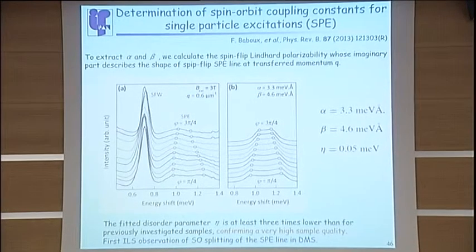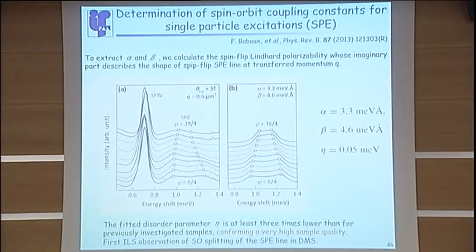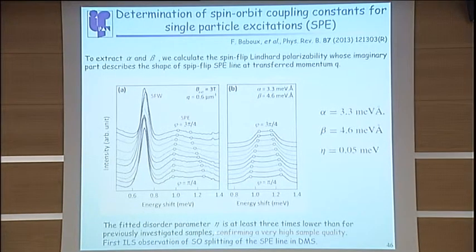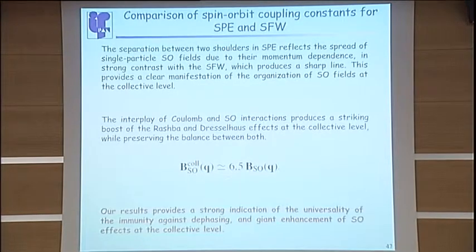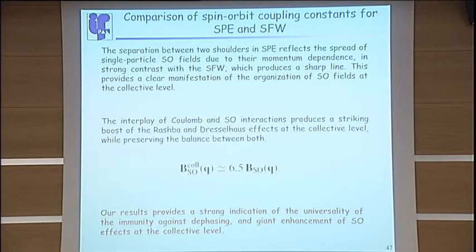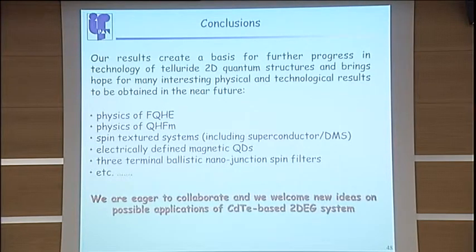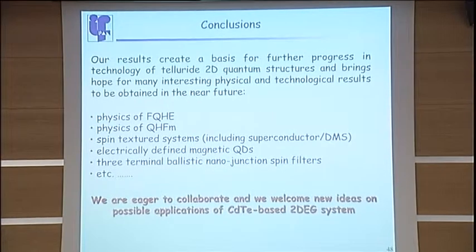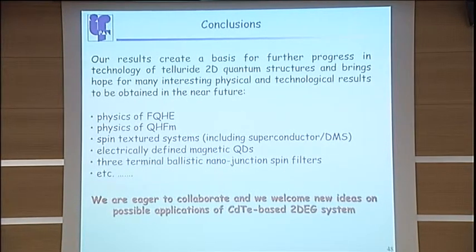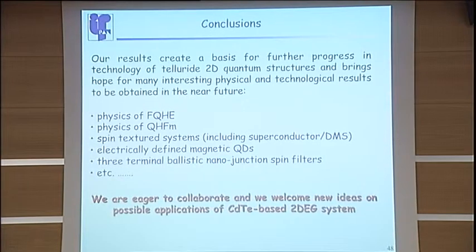And from the point of view of a crystal grower, it's always good to hear that our samples are good. And they said that this disorder parameter in our sample was a few times better than in any previous sample, confirming that the quality of the sample was really very good. So from these studies, they have determined, as I said, the enhancement of the spin orbit field for this spin wave excitation.